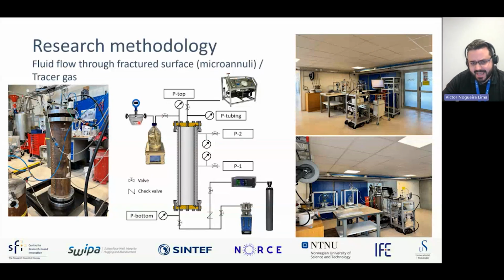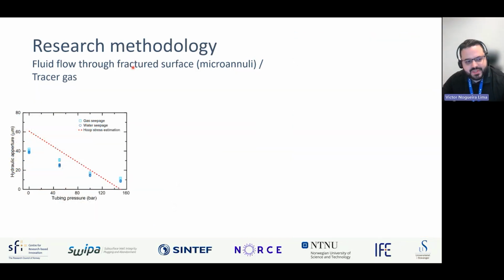Besides that, we also had this pneumatic pump that was connected to the inner casing. By changing the pressure of the inner casing, we could play with the microannulus size of this fracture surface, so we could have different sizes of microannulus over there. Then we started to characterize the cell, beginning with single phase measurements. With no tubing pressure, we found a hydraulic aperture, the microannulus size, of 40 microns. We applied 50 bar pressure and found around 30 micrometers. We applied 100 and 150 and so on, and then we had this behavior.